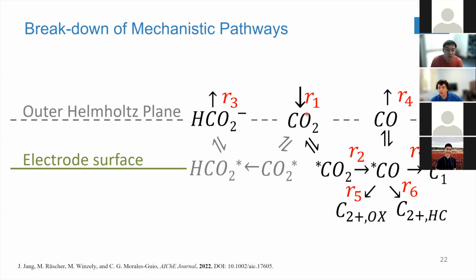We know how many molecules of CO2 per second per square centimeter are being transformed to either formate or CO. What we know in electrocatalysis is that these two pathways, to formate and to carbon monoxide, are different. So you can take carbon dioxide and make carbon monoxide, and carbon monoxide is the main reaction intermediate for the production of methane, ethylene, and different alcohols. And then R4 will be the carbon monoxide that escapes that CSTR space, that volume near the surface of the electrode, and we can also measure that experimentally.